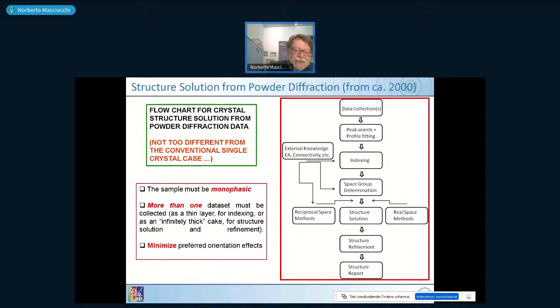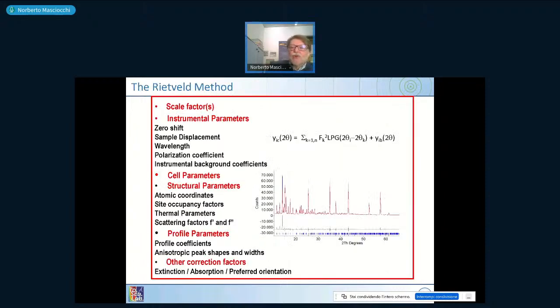So powder diffraction is still a good method, but it needs some external knowledge and some good skills to get the structure information from the powder diffraction data. The Rietveld method, which I mentioned before, uses a complex function, and the important thing is that within this, Fk squared, the square of a structure factor, is the structure information. Everything else is metric information, where the position of the peaks and background all together form a different complex system. So there are many factors which are to be refined.